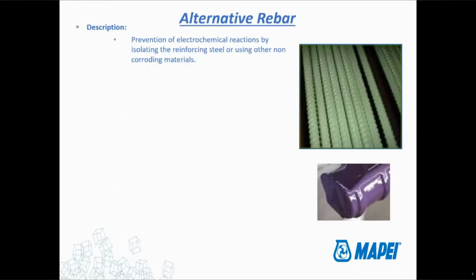Then there's alternative rebar. This could be your epoxy coated bar, your FRP bars. Basically, it's putting something around the reinforcement steel or using a non-corroding material for the reinforcement in order to basically prevent corrosion. So again, this could be epoxy coated, stainless steel. Then there's the carbon and the fiberglass bars, the FRP bars. Those just don't corrode at all.